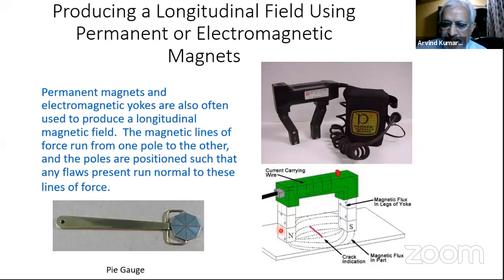That is why at each location, you have to do this twice. You fix the yoke at one portion like this, and you see whether there are defects or not. And then at the same location, you turn the yoke 90 degrees so that the orientation of the field will be different, and then again you try to see if there are defects. So at each location, you have to do it twice